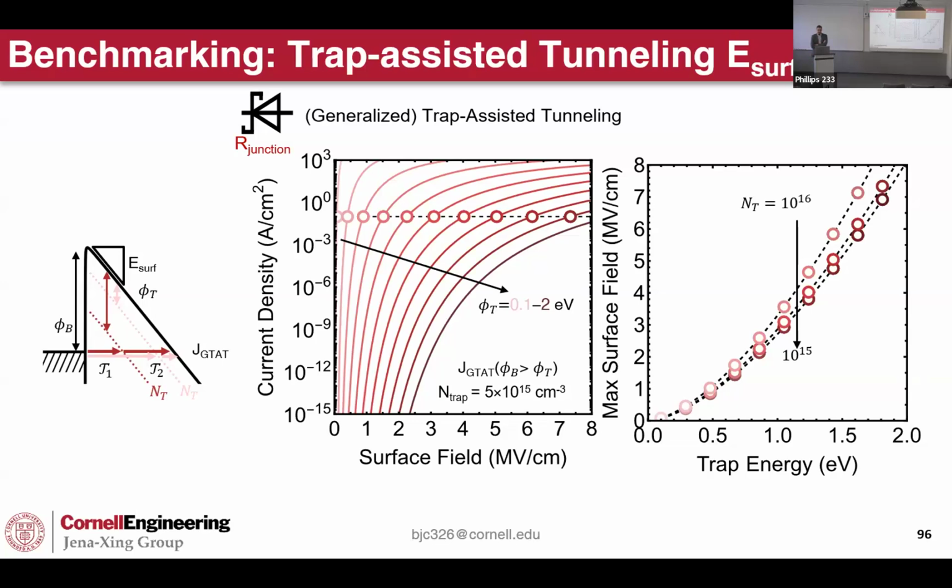You can correct me, but I believe the state of the art nowadays is low E15, which is still very reasonable. But they're all below 1.5 eV, right? So there's nothing in that region. I mean, there's iron, but you don't want iron up there. But then there's the intentional and the unintentional defects. Of course, I didn't get to it in this talk, the native defects. I was thinking about gallium vacancies. I thought they were deeper.